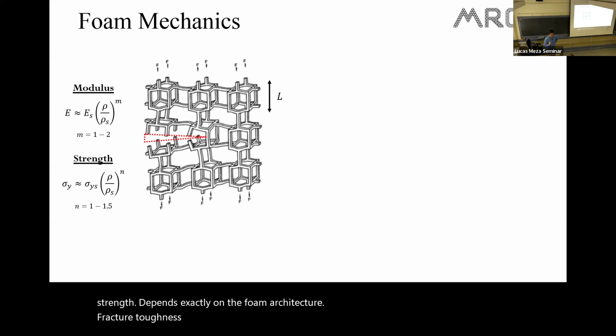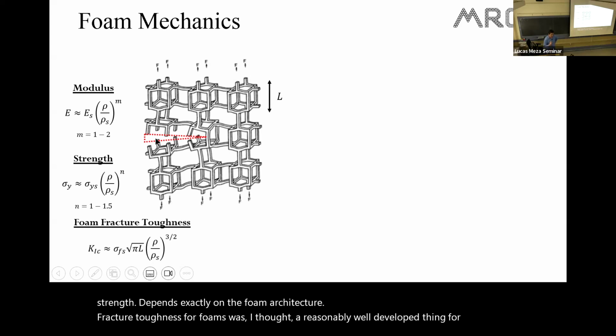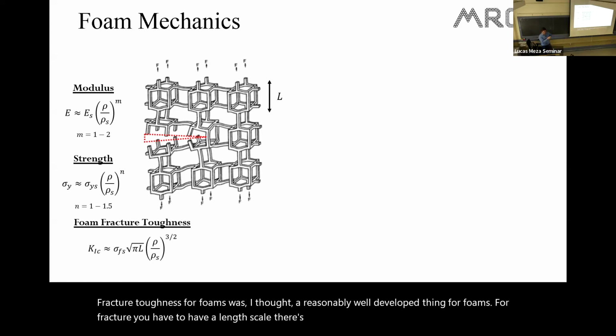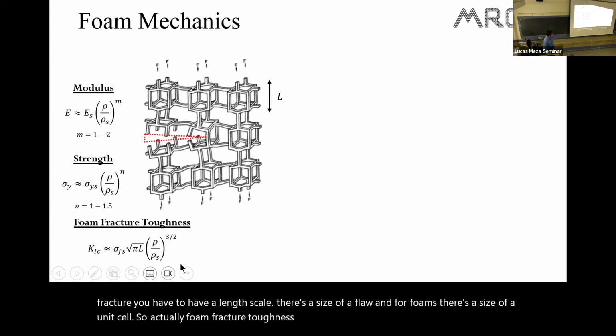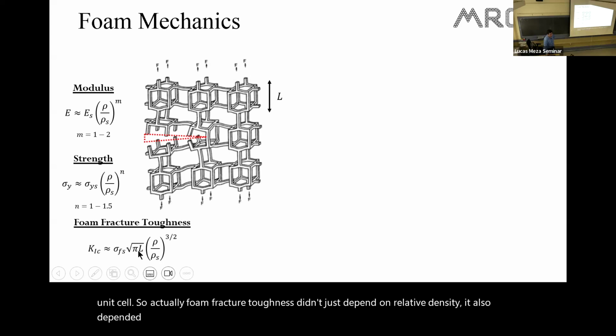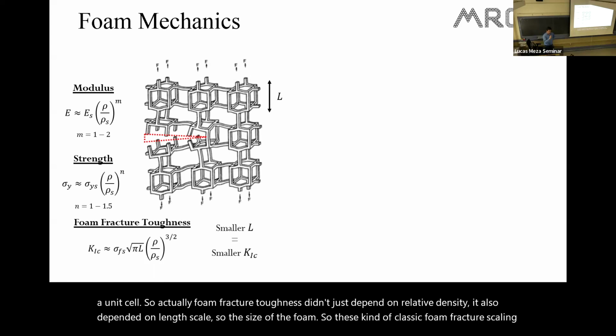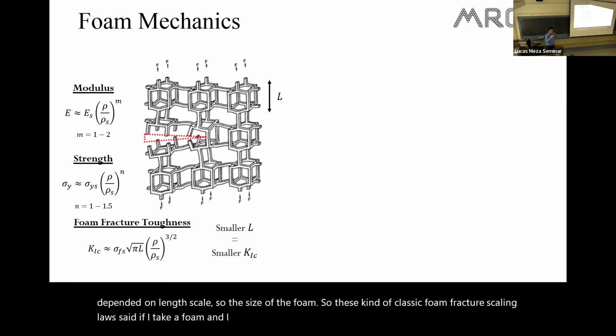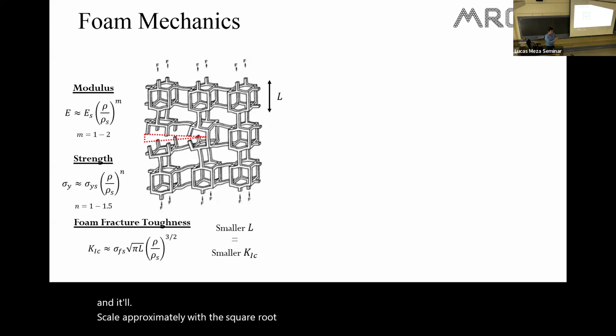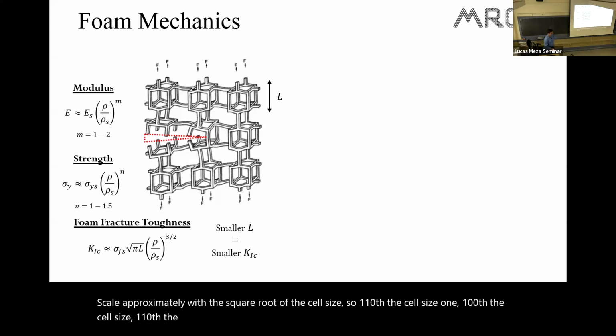Fracture toughness for foams was, I thought, a reasonably well-developed thing. For fracture, you have to have a length scale. There's a size of a flaw, and for foams, there's a size of a unit cell. So actually, foam fracture toughness didn't just depend on relative density, it also depended on length scale, so the size of the foam. These classic foam fracture scaling laws said, if I take a foam and make the pore smaller, I will end up with a less tough material, and it'll scale approximately with the square root of the cell size. So 1/100th the cell size, 1/10 the toughness.